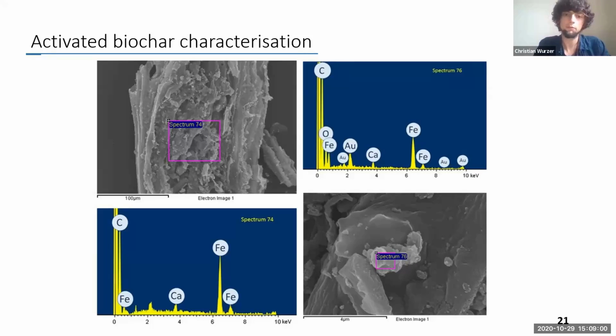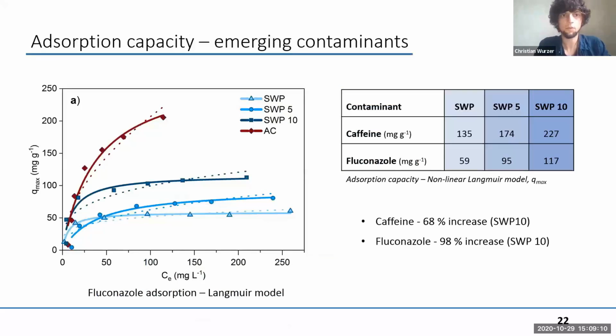From this spectrum, we see that these are the iron containing particles attached to the surface in a spherical shape. And now, last but not least, the adsorption capacity of our activated magnetic biochars. We used a commercial activated carbon as a reference material to see how good we are. So on the left, you see the fluconazole batch adsorption test.